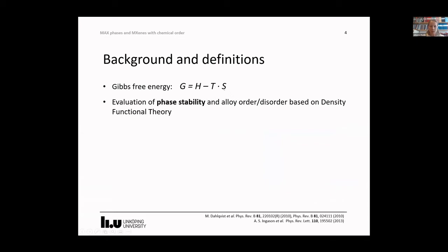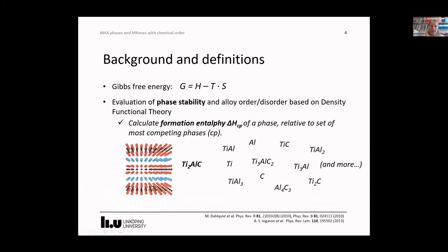So Gibbs free energy is defined as the enthalpy minus the temperature times the entropy. And this is the expression that we use to evaluate the phase stability, the theoretical phase stability of both known and hypothetical materials using density functional theory. In other words, we try to theoretically predict which materials are likely to be formed in synthesis experiments. For alloys, we also predict if we get a solid solution or chemical order or disorder. To evaluate the phase stability, the most basic approach is to calculate the formation enthalpy of a phase relative to a set of most competing phases. If we take titanium aluminum carbide here as an example, it is based on titanium, aluminum, and carbon.